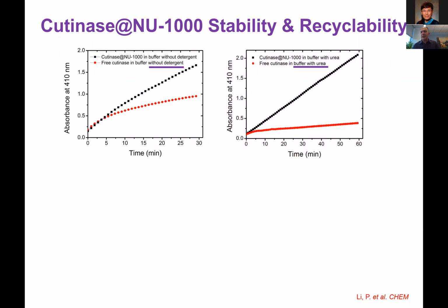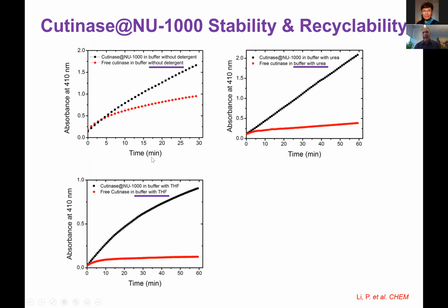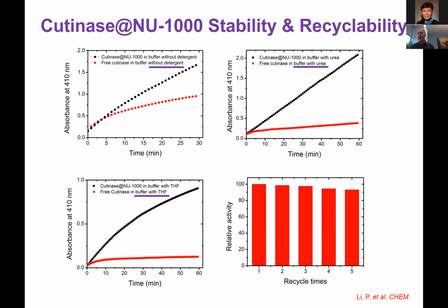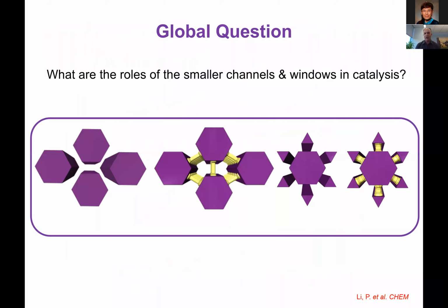Now, let's add urea into the system. Urea is really the kiss of death for enzyme. It breaks those hydrogen bonding very quickly and denatures them. And you could see the free enzyme is dead from the beginning. Our composite keeps going. We could now start adding acetonitrile, THF, organic solvent. Our composite keeps going. More importantly, now we could start filtering our composite and reusing it. And remember, every time we use it, that's more turnover numbers. That means we're keeping the turnover frequency and we're increasing our turnover numbers.